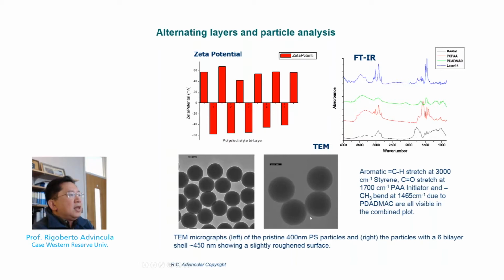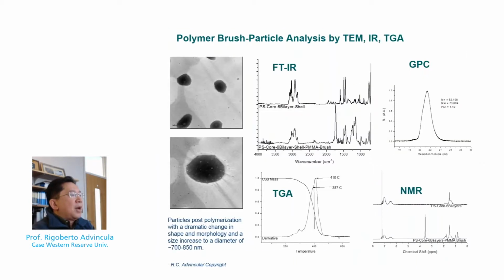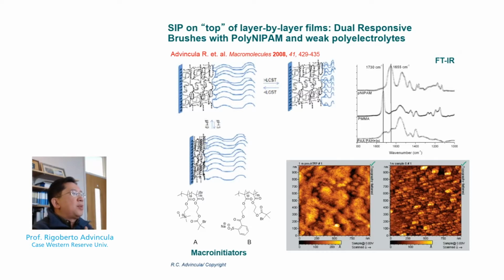And we can also track this by TEM and FTIR as well. IR confirmed the presence of the macroinitiator on the surface. This was then followed by polymerization of the corresponding polymethyl methacrylate. So here you can see the particles after grafting the polymers. The core is slightly visible on the surface, but then the surface was coated with PMMA. Again, to characterize this type of brushes, we would then degraft the polymer or dissolve the PS, and then we will characterize by NMR, GPC, or TGA. In fact, one of the consequences of using ATRP is sometimes we have polymers that are bound or not bound on the surface, which we can use also to characterize the efficiency of the ATRP.